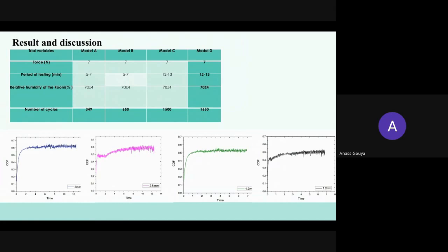The development of the coefficient of friction for various contacts and insulation thicknesses was examined in this study, along with the effects of insulation geometry on friction and wear in the abrasion test. The coefficient of friction first rises quickly at steady speed as the test duration increases, peaking at roughly 0.664 when a blade exerts a 7 Newton force on the insulation.